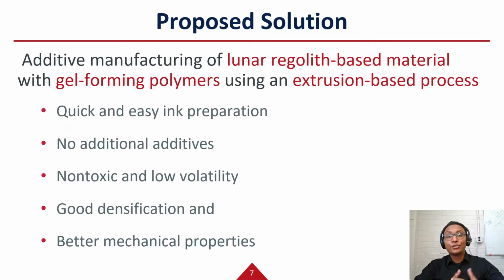For utilizing both regolith and water, we investigated the use of a hydrogel-forming polymer which is known as pluronic. The regolith can be easily and quickly mixed into the pluronic hydrogel at low temperatures. It doesn't even need any additives. The generated aqueous ink is non-toxic and it has low volatility. This ink can be used in extrusion-based processes and can be sintered to produce dense parts with improved mechanical properties.